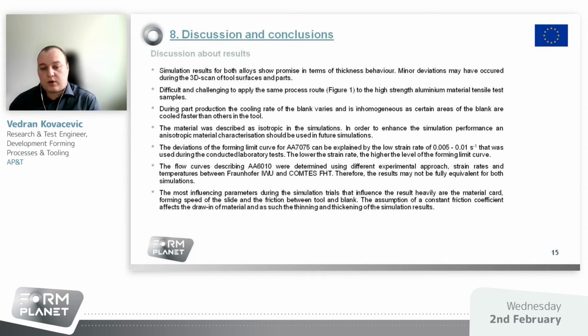The materials were described as isotropic in the simulation, which also might lead to less accuracy of the calculated results. In future projects, an anisotropic characterization of the material should be investigated, of course. The friction coefficient is one of the most impactful parameters in hot forming. In the simulation, it was assumed to be constant. However, in reality, the friction depends on temperature, speed, pressure, and lubrication amount. The friction affects the drawing of material and in the end, the thinning and thickening results.